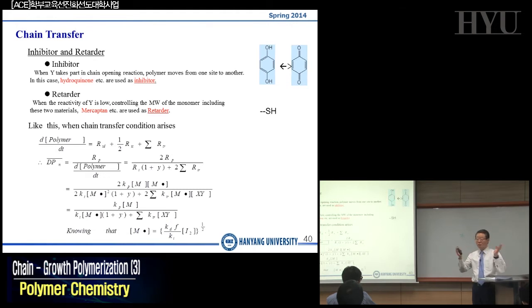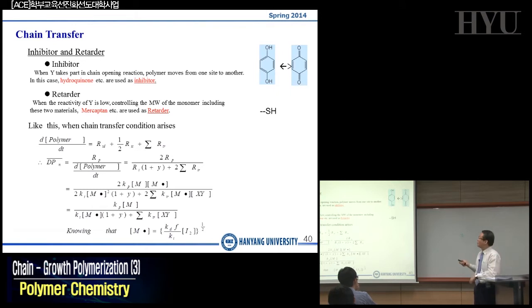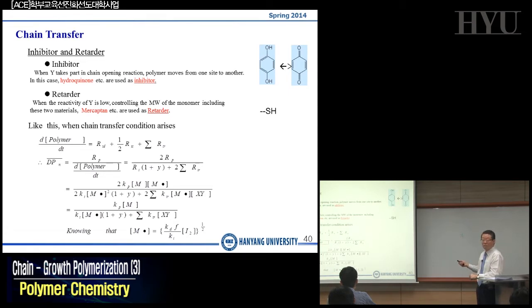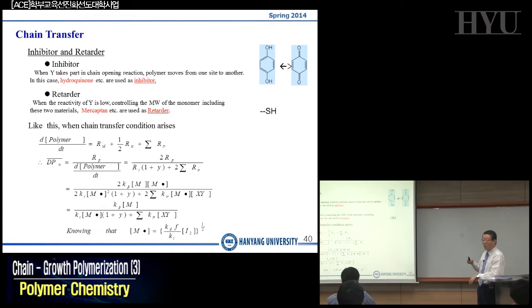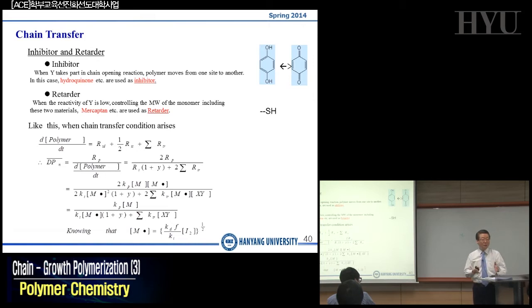The component for an inhibitor is usually called hydroquinone. Hydroquinone loses protons from its hydroxyl group. If you lose a hydrogen radical, one of the radicals will combine here because it's not stable, and one of the double bonds will rearrange electrons so that you have an exchange reaction between the hydroquinone and a diol. From this equilibrium reaction, hydroquinone will act as an inhibitor of your radical polymerization reactions.